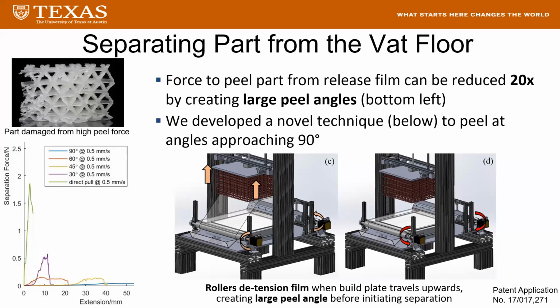After the curing step, which again is illuminating from below that film, the rollers detension the release film, allowing the part to be raised up without exerting any force onto the cured layer. At the desired layer height, the rollers will retension and initiate separation. And by peeling off the release film from our cured structure at these high peel angles, we're able to decrease the separation force by over a magnitude compared to if we just tried to lift the part straight off of tension Teflon.